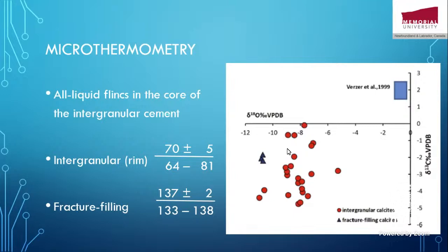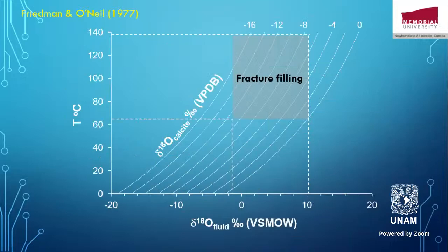This, of course, as I said, is because the diagenetic fluids rarely have high dissolved carbon dioxide to reset the delta carbon 13 signature. Because these were calcites, not dolomite, we apply the calcite equation of Friedman and O'Neil, 1977, and from the homogenization temperature, one can estimate the delta O18 of the parent fluid. It's probably between minus 2 or so and plus 10. And obviously, the higher the temperature, the heavier the delta O18 of the parent fluid, because the fractionation of oxygen isotopes decreases with increasing temperature.